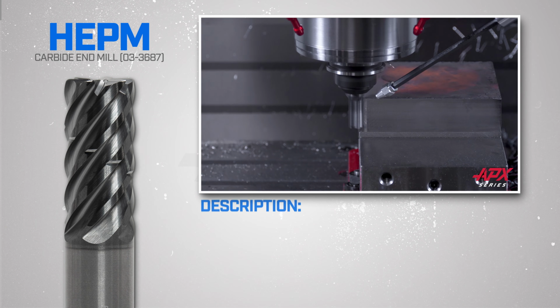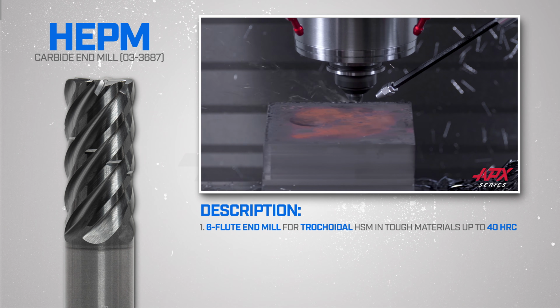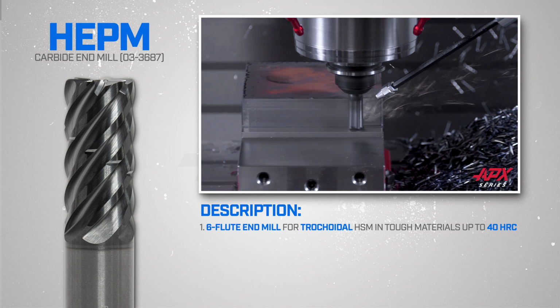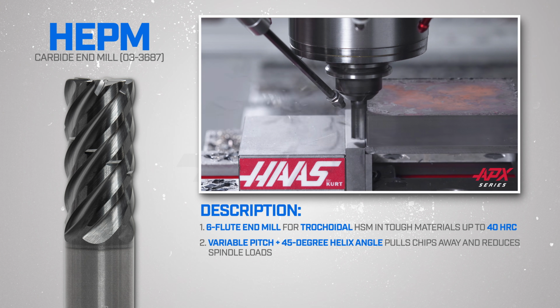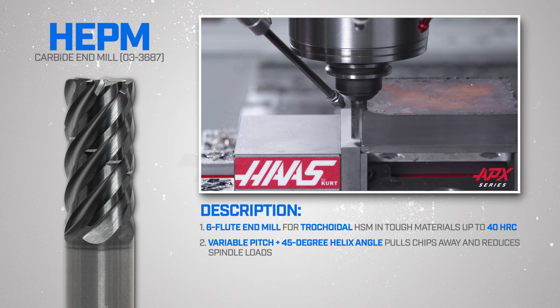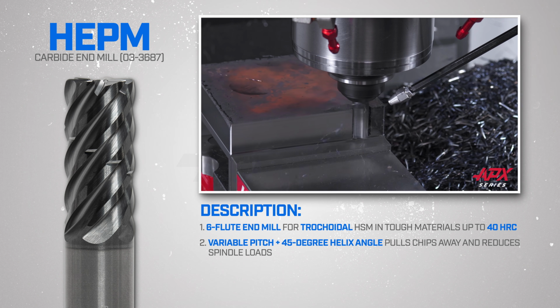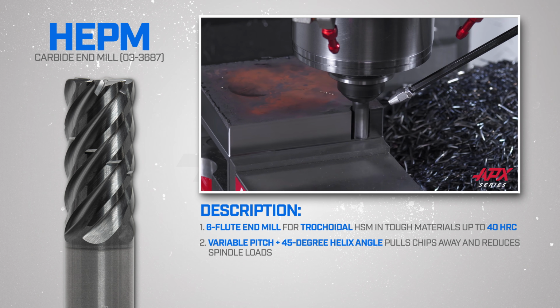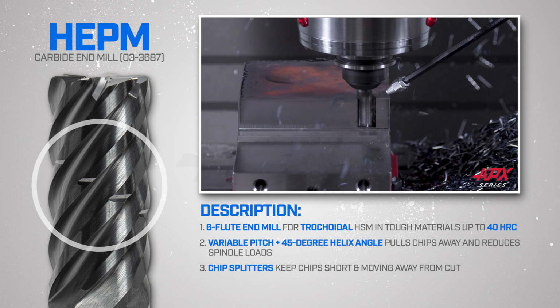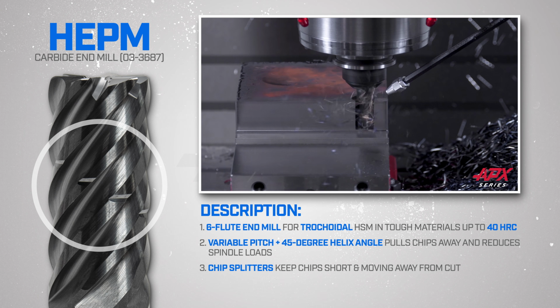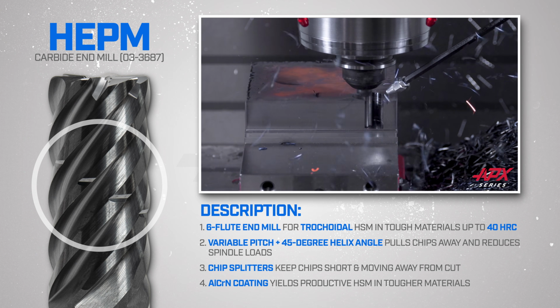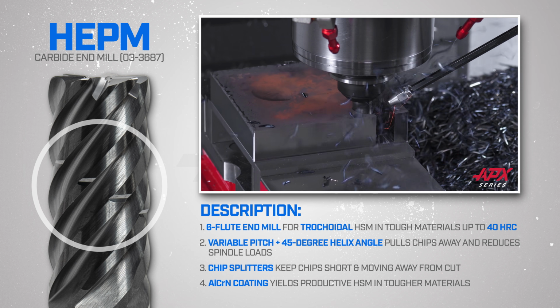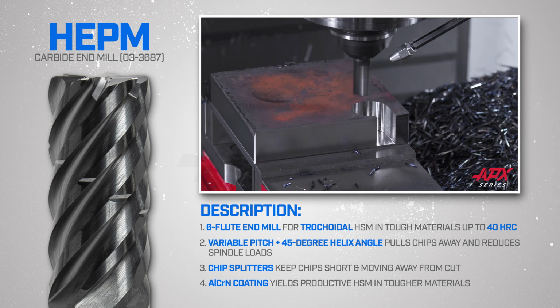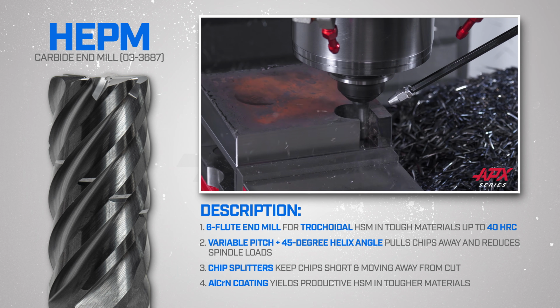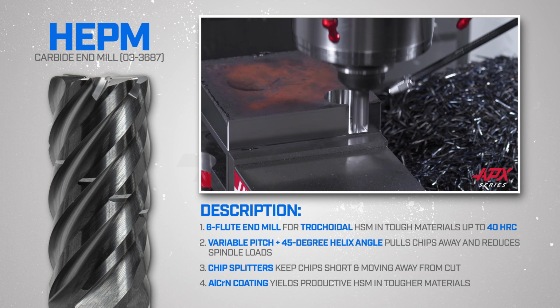This is our HEPM 6-flute end mill that is designed specifically for high-speed trochoidal milling, tougher materials up to 40 Rockwell C. Premium micrograin carbide, of course, with variable pitch flute spacing and a high 45-degree helix angle to pull chips away from the cut and reduce spindle loads on these harder materials. And you can see here along the flutes, this tool has these chip splitters. That means when you're machining at larger depths of cut, the chips are broken into pieces so they are more easily moved out of the way of the cutting path. With the slippery aluminum chromium nitride coating protecting the tool, you'll get productive, high-speed milling in harder steels, tough stainless, irons, and even high-temp alloys. This is high material removal rate milling that can live with the pressure.